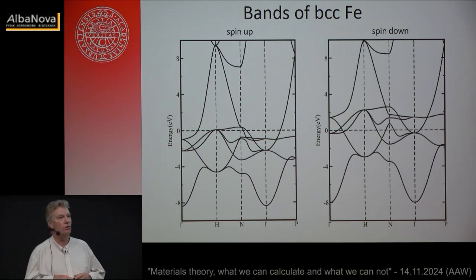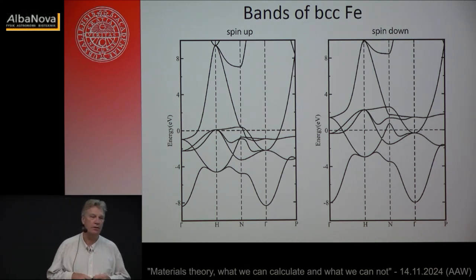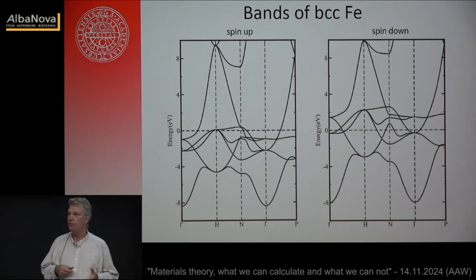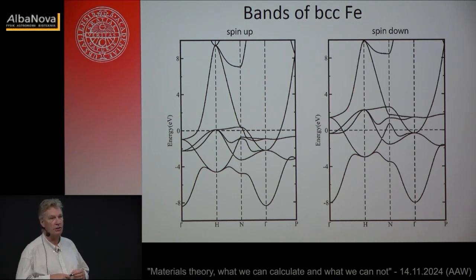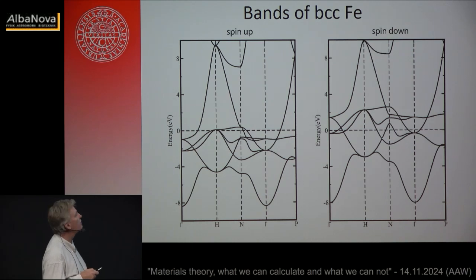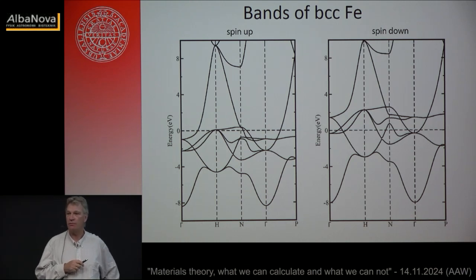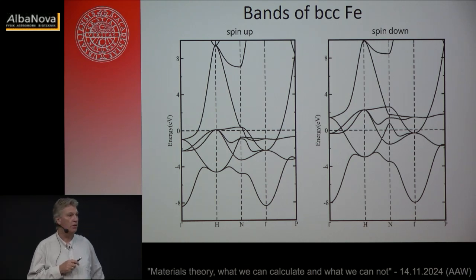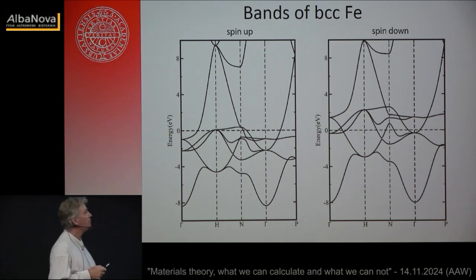And this is something that you can also, many of you do this, is connected to experimental measurements. You can measure the energy dispersion, energy versus crystal momentum in an angular resolved photoemission study. So these energy bands can be mapped out and followed by ARPES measurements, and they never ever really agree. And I'll come to that at the end of this talk. So this is not something that really we can compare to experimental data. If it agrees, it's just luck, or it's not really supposed to be there.